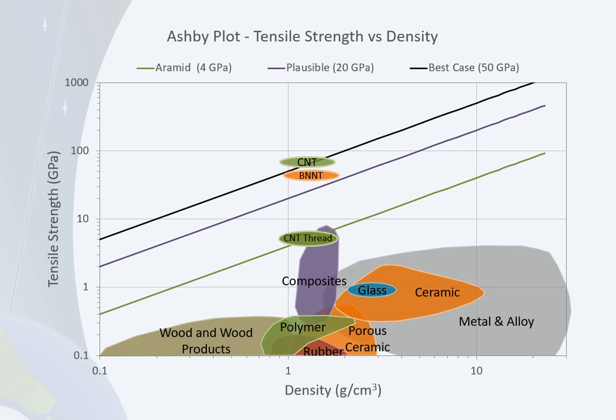A little bit below carbon nanotubes, but still well past our plausible line, we find boron nitride nanotubes. They're a bit more like a ceramic in terms of their chemistry, but as we'll see, they behave a lot like carbon nanotubes in terms of their structure and strength. So while not quite as strong, they have about the same density and are still quite strong, and so are a good candidate. But that's all molecules. If we get above the molecular scale, the only thing even close is carbon nanotube threads. That's exactly what it sounds like.